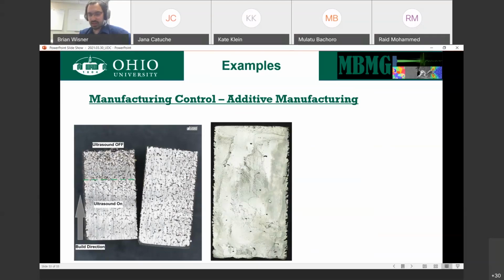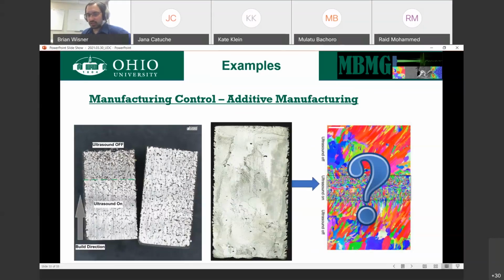We're in the process now of doing an EBSD scan to see if we actually achieved the change in the grain structure. What should be happening is that with our ultrasound off, we have a grain structure that looks like this. With it on, we refine it. So the properties in this region are going to be different than the regions around it.